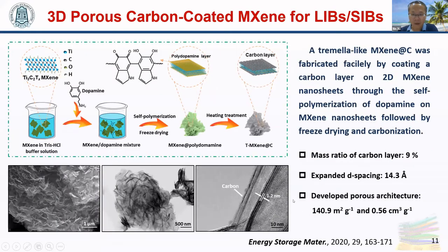A tremella-like MXene was fabricated facilely by coating a carbon layer on 2D MXene nanosheets through the self-polymerization of dopamine on MXene nanosheets, followed by freeze drying and carbonization. The self-polymerization of dopamine on the surface of MXene not only facilitates the transformation of 2D MXene to a tremella-like structure, but also forms a thin carbon layer on the MXene surface. The carbon layer, with a mass ratio of 9%, protects the MXene from air oxidation and self-aggregation. The 3D porous carbon-coated MXene exhibits expanded spacing and a developed porous architecture.